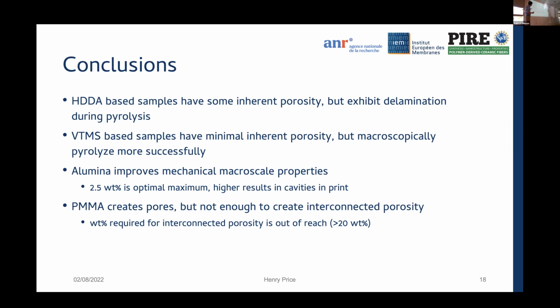And with the addition of alumina, this does improve mechanical macroscopic properties. And again, I must add the caveat that this is not a quantitative evaluation. I did not conduct mechanical testing, but from a qualitative analysis, this was consistent. And the optimal percentage was 2.5 weight percent, so quite low. Higher than that results in printing issues from the cavities and the high viscosity.